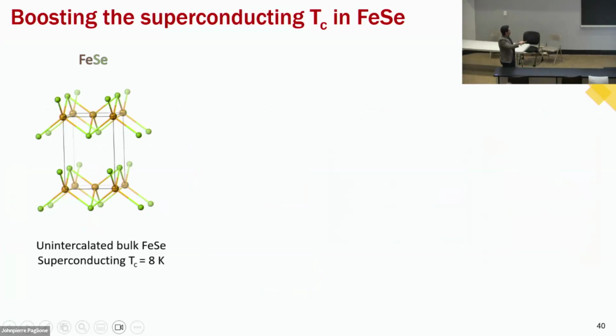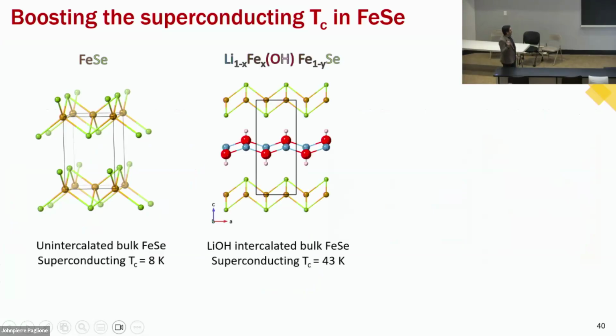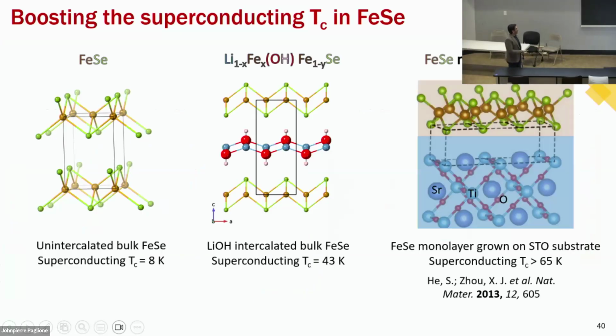So unintercalated iron selenide is pretty remarkable in itself. It's superconducting at 8 Kelvin. And then if you intercalate it, you can get up to 43 Kelvin. And then there was this report that you could get a monolayer on strontium titanate and you could get up to 65 Kelvin. There was one that was 100 Kelvin. So, we'll see how true that is.